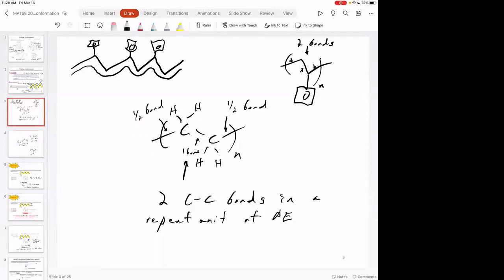So we've calculated X bar N, or the degree of polymerization, because we can get that from the molecular weight and the M0. But remember, for this calculation, you need to think about how many steps you're taking in this contour length or fully extended chain or random walk, etc. So you need to remember to count the number of bonds in the repeat unit in order to get these right. Otherwise, if you use the degree of polymerization, your answers will be 50% of what they should be. And you can bet that that is probably going to be one of your choices on the exam, because that's an easy mistake to make.